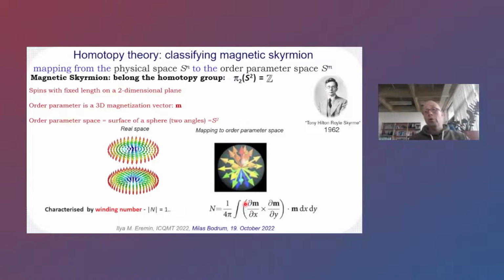So let me just, for those of you who are not working in the field of skyrmions, remind you that this is a topological texture that can be characterized by a particular homotopy group, which is basically mapping the physical space spin orientation to the order parameter space. And in this case, for the skyrmions, you have spins with a fixed length on the two-dimensional plane, and your order parameter is a 3D magnetization. So what is actually happening is that your order parameter space becomes the surface of a sphere, described by the two angles as S2. And you can have topological defects which you cannot easily remove in this case.